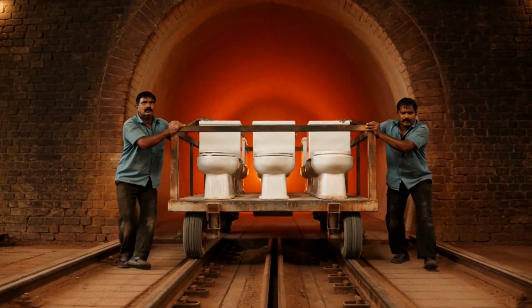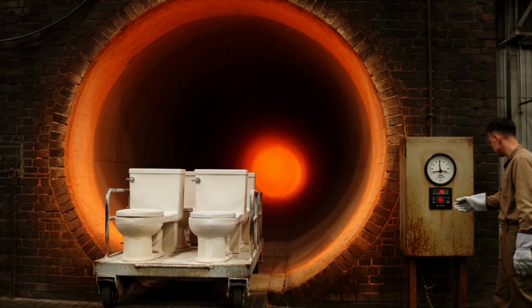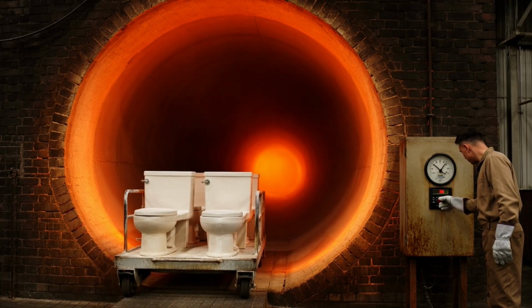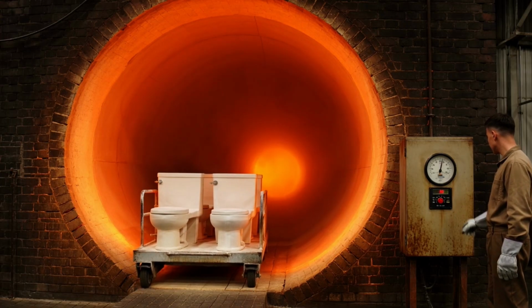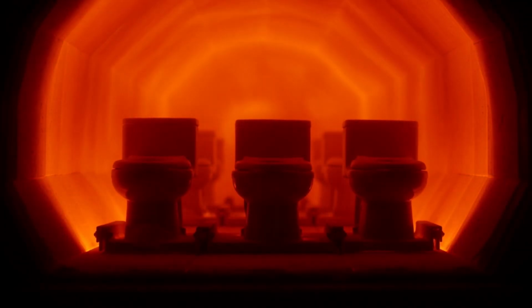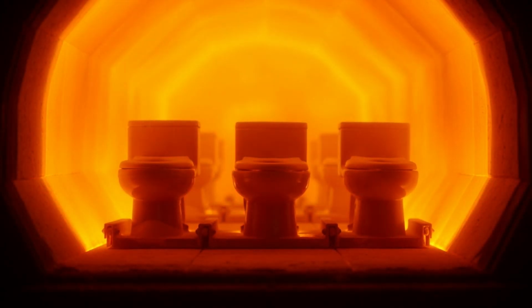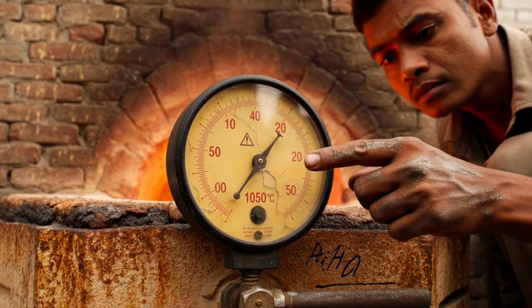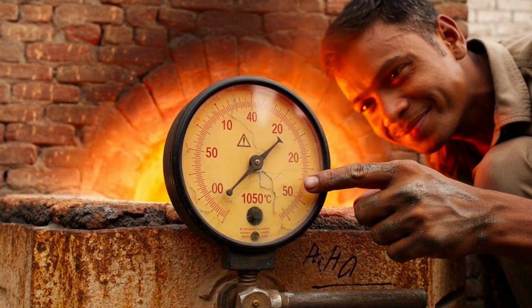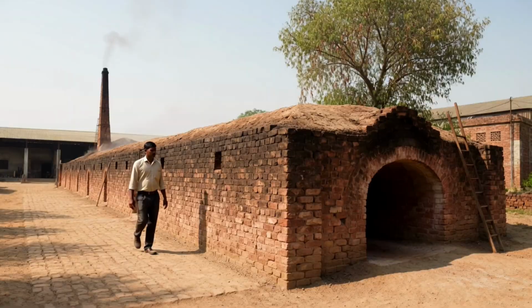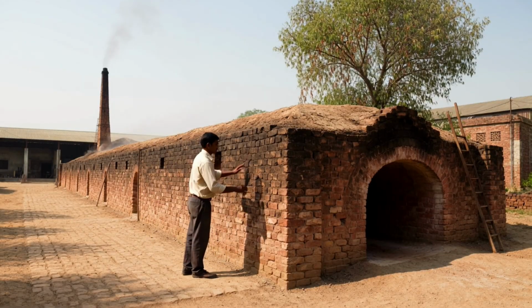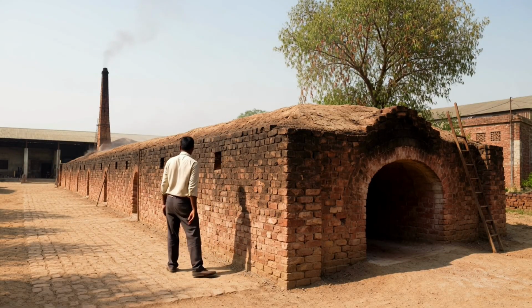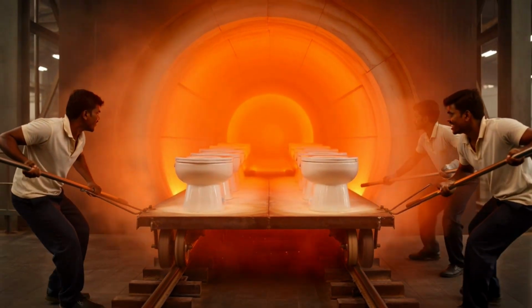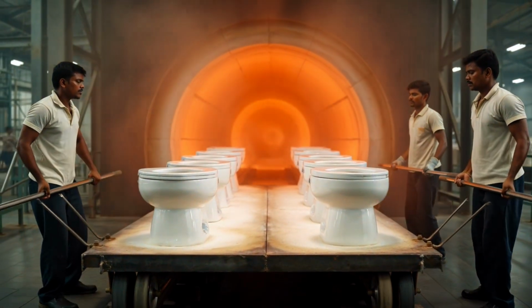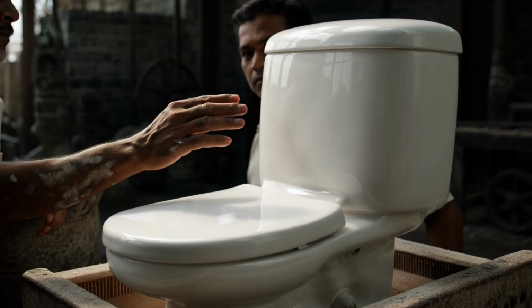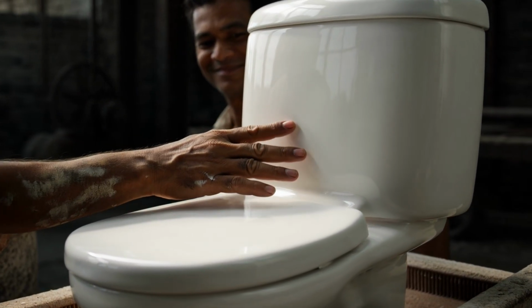Inside the tunnel kiln, temperatures climb to around 1,050 degrees Celsius. That's nearly 1,900 degrees Fahrenheit. At that temperature, something remarkable occurs. The clay particles fuse together at a molecular level, becoming a hard, dense, non-porous ceramic. And the glaze, that chalky white coat that went on dull and dry, melts and flows into a smooth, glassy surface. As it cools, it hardens into the brilliant, glossy white finish that a ceramic toilet is famous for.